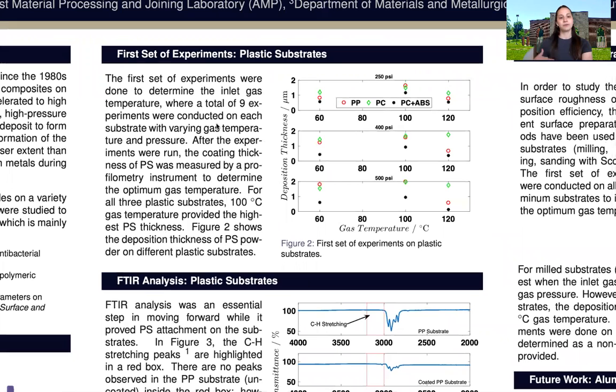The middle column in this poster shows the results for plastic substrates. We tried 3 different plastic substrates: polypropylene, polycarbonate, and a mixture of polycarbonate and ABS. Figure 2 shows the deposition thickness of polystyrene with only 2 passes with varying gas temperature and pressure. The top graph is at 250 psi in varying gas temperature, and the middle one is 400 psi, and the third one is 500 psi. We wanted to determine the best temperature for most substrates, so we went with 100 degrees C.